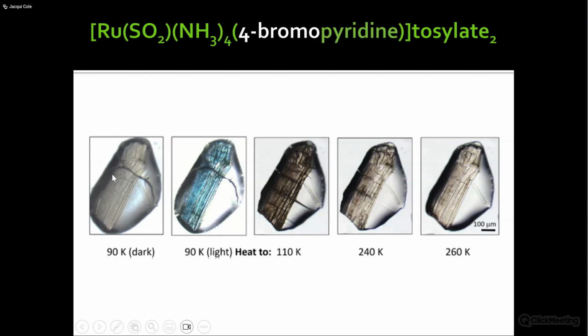This is what happens. So this is the dark state. This is the glue, by the way. Well, it's the oil frozen, and then it's photochromic, and you see all these stripes. These are the striations. You see how strange that is. And then that's the light state at 90 Kelvin. Then you go up to 110 Kelvin, and actually I heated up even a bit more, and I keep heating up until it gets back to room temperature, and it's pretty much recovered. It didn't quite survive. Actually, that was already there, so that's okay.